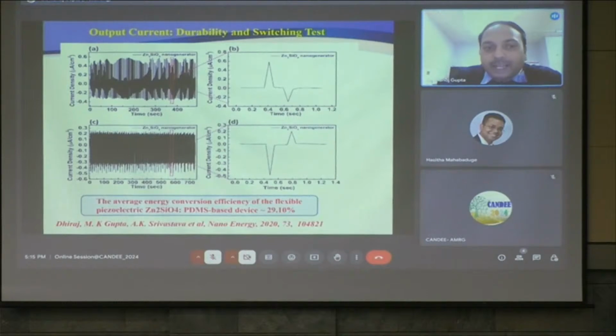Okay, so this also shows the durability. You see, the current density is highly durable, even up to 700 cycles, up to a few thousand cycles, there is no change in the intensity of the electric signal, and the conversion efficiency was 29%.